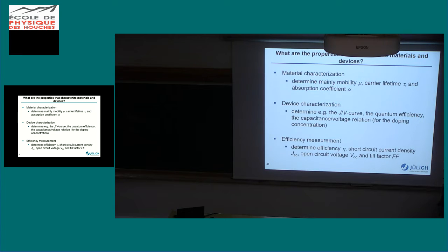And this is what we already heard also this morning, briefly in passing, that the diffusion length should be larger than your device thickness. And the diffusion length is the mobility lifetime product, essentially. How fast and how long you can move, that's mobility times lifetime. And if there is an upper lifetime, which is given by the radiative lifetime, you just have to have the mobility large enough that the product is good enough to give a good solar cell. And everything else is not necessary.